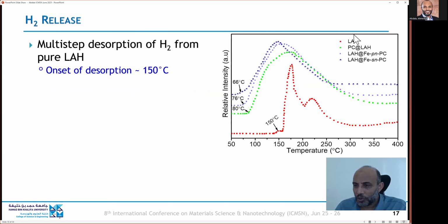So we test first the pure lithium aluminum hydride, and we can get the typical multi-step release profile associated with the steps that we described before. We have a 150-degree onset of hydrogen release. If we support it on porous carbon, we get significant enhancement because of the high surface area and the distribution of the lithium aluminum hydride. The onset temperature is reduced to 80 degrees, but the maximum hydrogen release is still almost at the same temperature. If we use the catalyst doping with the post-confinement approach, we reduce the onset temperature to about 76. We reduce the maximum release temperature to about 175, 180 degrees.